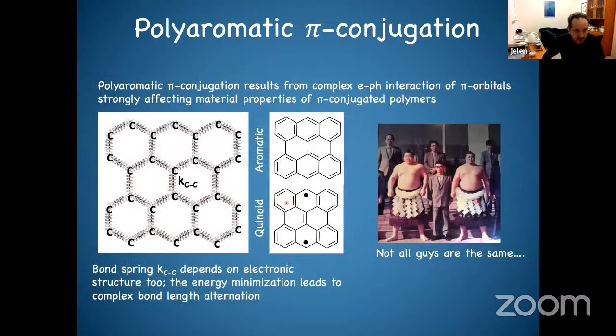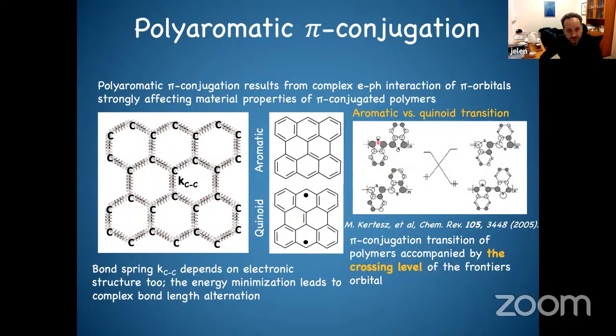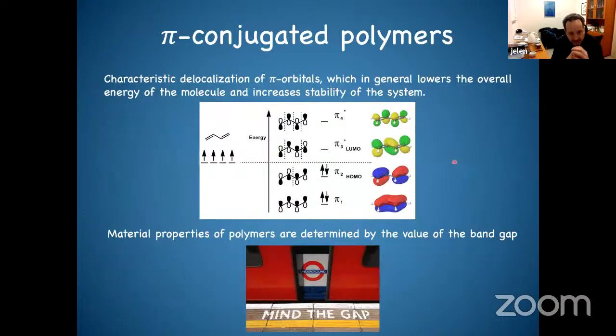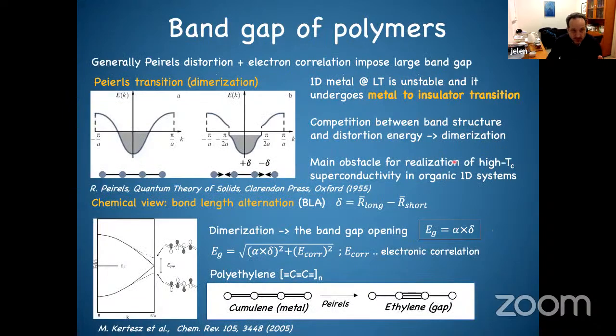In principle, you have to see that each carbon bond has a certain spring, and it interplays between how to minimize the deformation of these springs and satisfy the lowest correlation. So at the end, if you look at these, each bond is not equal, okay? Each of them is a little bit different. That also has some implication for the electronic structure, as I will show in a minute. And importantly, this bond length alternation is somehow responsible for opening the band gap.